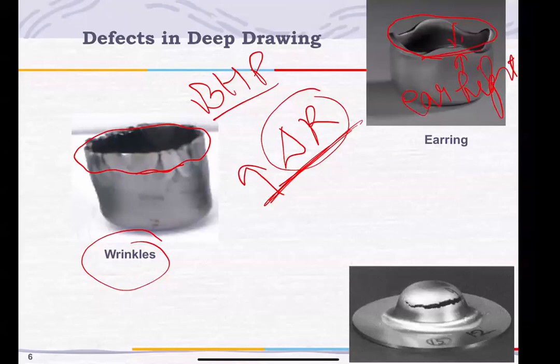And then another very popular defect is fracture at the cup bottom. This appears either when the draw ratio exceeds the limiting draw ratio, or when the blank holding pressure is high. Because of these two reasons, fracture appears in the drawn component.